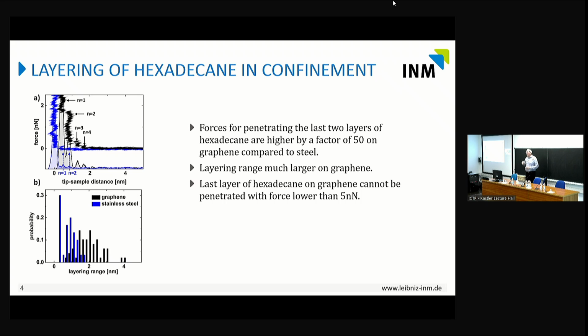Now, if you do the same above graphene in hexadecane, that's the black curve, you actually see that there's a layering. You can observe layering of the hexadecane in the confinement of the tip. You see 4 layers, 3 layers, 2 layers, 1 layer, and we could not penetrate the last layer of hexadecane on graphene without breaking the whole system. And you can also see that we have a distribution of many, many curves and systems of the layering range. And you can see here that the layering range extends up to 4 nanometers sometimes on top of graphene, but rarely more than 1 nanometer on steel. So somehow the graphene on the steel helps sort of building ordered layers of the hexadecane which can carry load, and that probably is the reason that the friction is reduced.